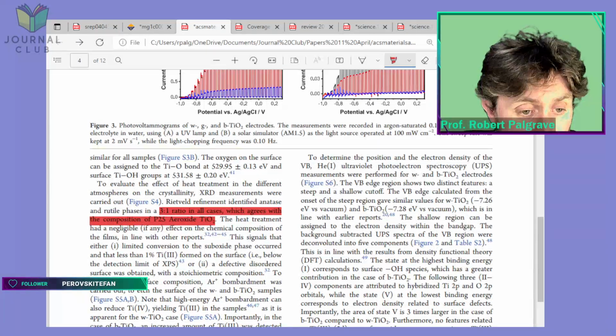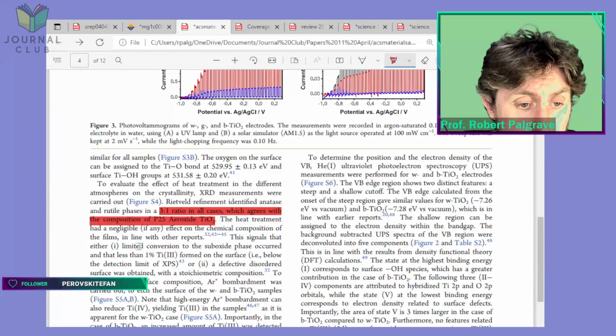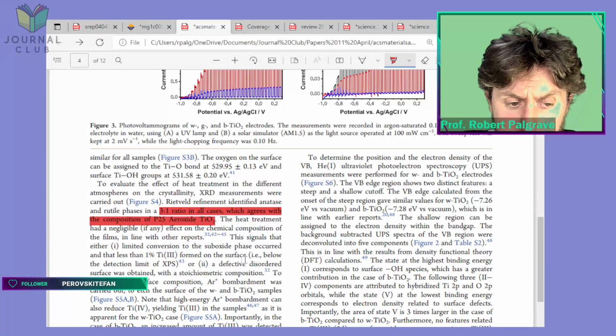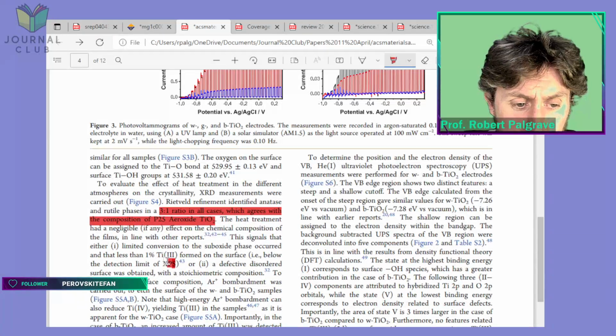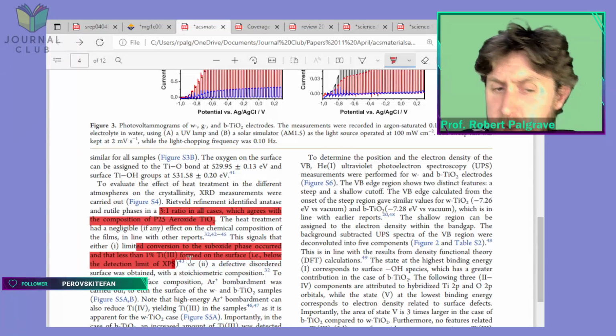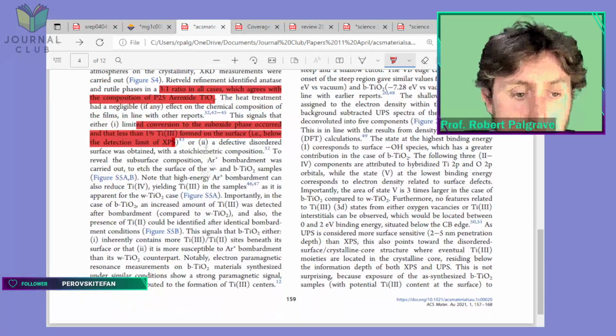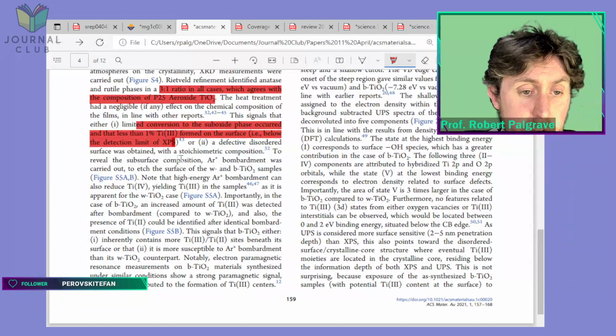Right, this signals that either limited conversion of the suboxide phase occurred and less than 1% Ti3+ formed on the surface, i.e. below the detection limit of XPS. Okay, I think this section really belongs here, because now they're talking about XPS again. Anyway, or a defective disordered surface was obtained with a stoichiometric composition.